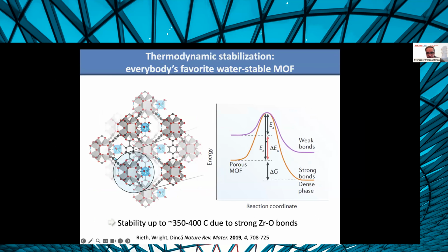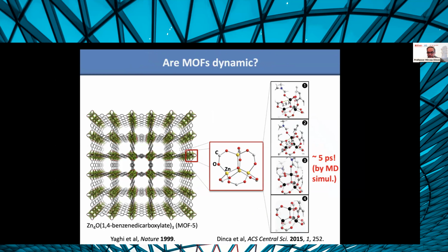Okay, so we can make water stable MOFs, which for catalysis is very important. Are MOFs dynamic? I will give you just one simple example from my own lab, where we demonstrated that MOF5 itself, which everybody knows, and that as having sort of pseudo-tetrahedral zinc sites, is actually very dynamic at the metal site on a time frame that is not actually reflected in techniques such as X-ray diffraction, but can be seen with NMR spectroscopy or MD simulations, and where basically it says that the zincs are not entirely tetrahedral, and they can become 5-coordinate or even 6-coordinate by binding of DMF solvent.